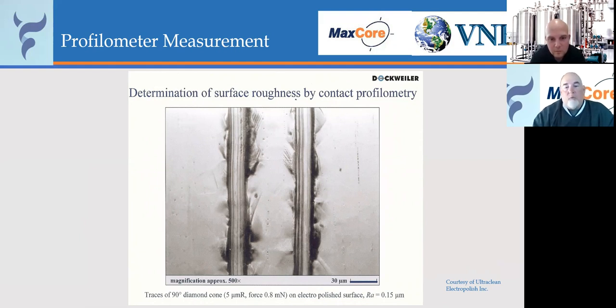So a lot of times whenever we're doing these types of measurements, when I was out doing this in the field, we'd make sure those RA measurements were there before we ever did the EP in order to make sure they were correct. Now, I'm not saying don't do this because you're talking about a minimal area. And yes, stainless steel will repassivate itself to a certain extent over time. So something along this line, if you allow it to sit in air, is not going to be a real problem. Okay? But you are scratching the surface when you use that. You are scratching the surface, absolutely.